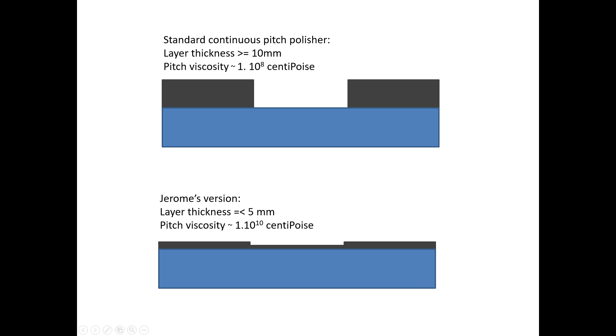So my method is different in the sense that I use a much thinner and much harder layer of pitch than normal. In comparison, the pitch I have is about 100 times more viscous and the layer thickness is more than 2 times lower. This reduces the amount of plastic deformation within a limited time frame by the same factors.